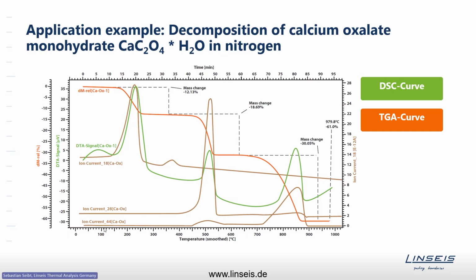In this case, the heating was performed linearly, so the sample was just heated, and what you see is a first mass loss at roughly 200 degrees, which is the loss of water, and this water loss is going hand in hand with an endothermic effect. This effect is the dehydration. As said, it's well known, it's the loss of water. You see the ion current of carbon monoxide and carbon dioxide do not show any effect. However, the ion current of water goes up, and that means water is released. The mass spec records some water that is released here.